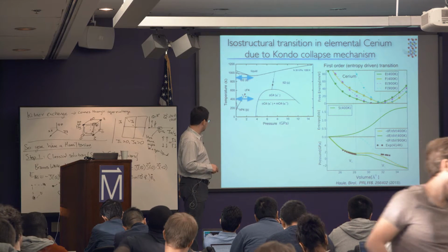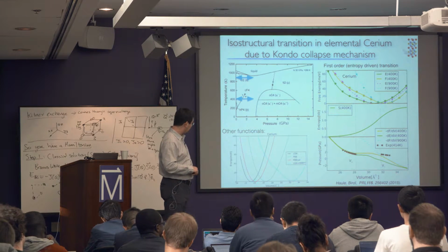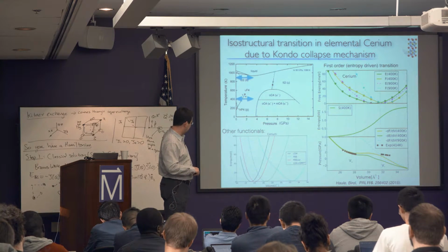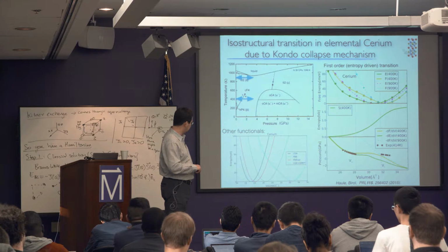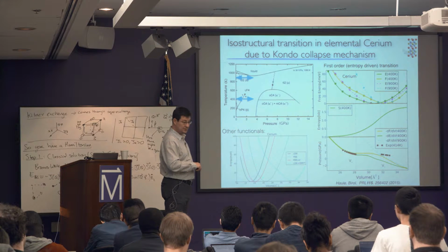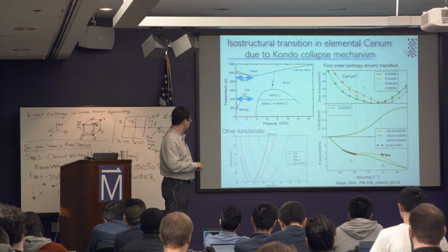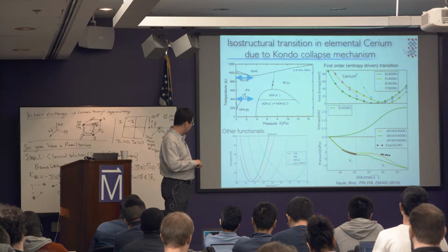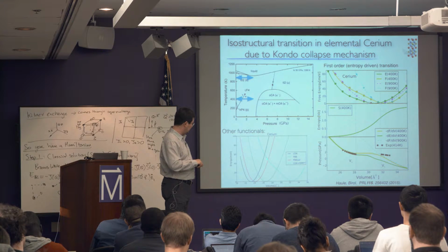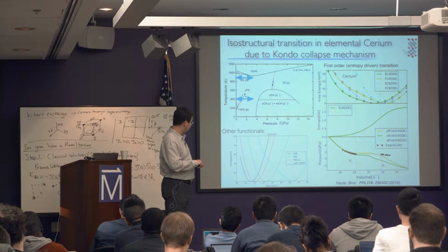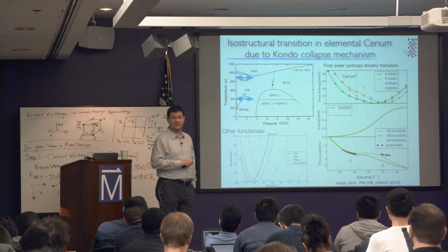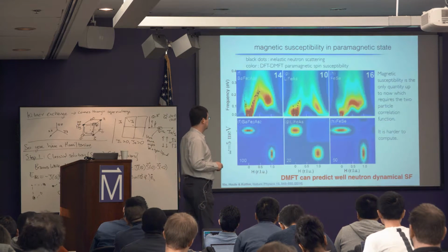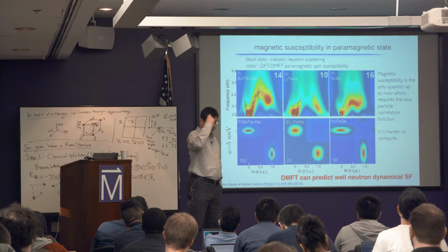And what's important here is that if you look at the other functionals, so LDA, PBE, PBEsol, you see none of those functionals has any indication of this wrong slope, or a very linear slope here. So the DMFT clearly has an indication of the Mott transition. All the others don't. So that's something that you cannot explain with any other functional.